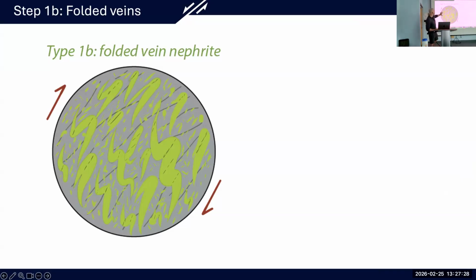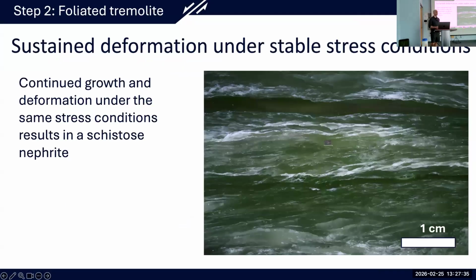And in fact, under these conditions, if the stress state that results in this folding is sustained and continued, eventually all of those grains will align themselves to a single orientation. So the grains will align themselves such that the long orientation is perpendicular to the overall compressive stress. And this, in geology, we refer to this rock as a schist. It has a foliation, and that foliation reflects that deformation. So if we continue to grow and deform under these sustained stress conditions, we're going to form a very well-aligned rock in which the tremolite have all their grains lined up within what we call a schistosity.